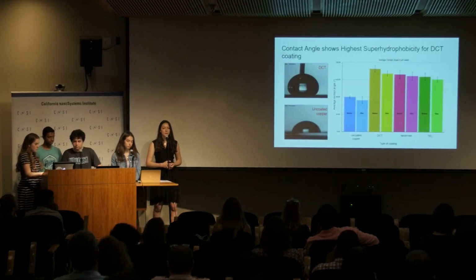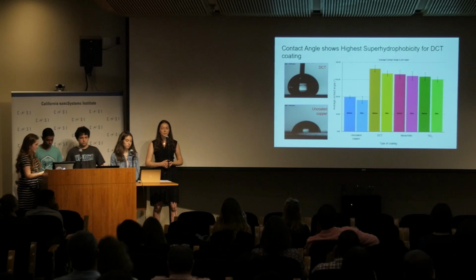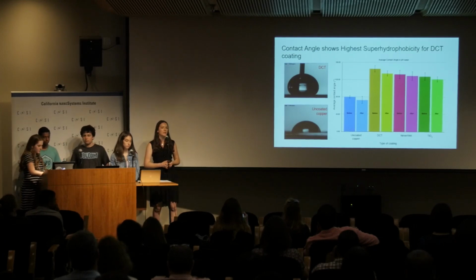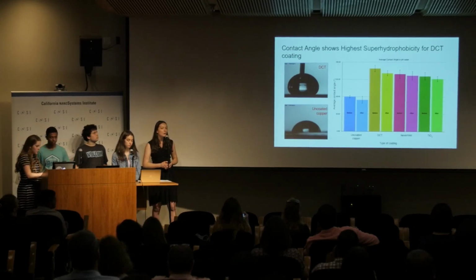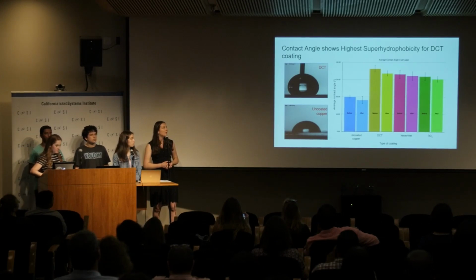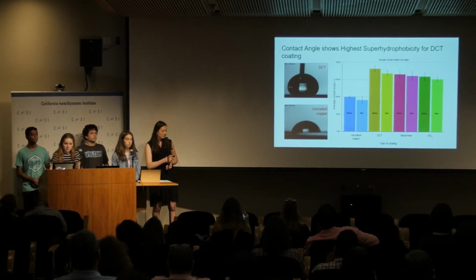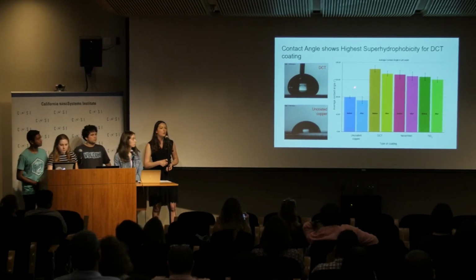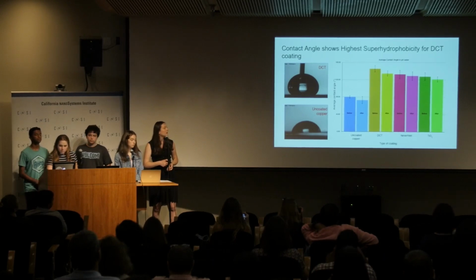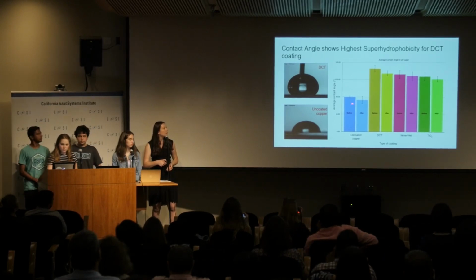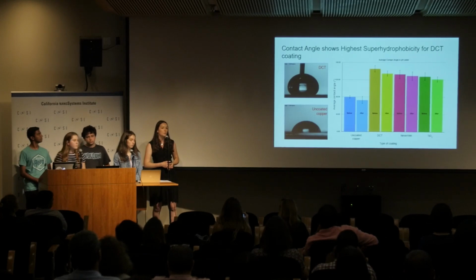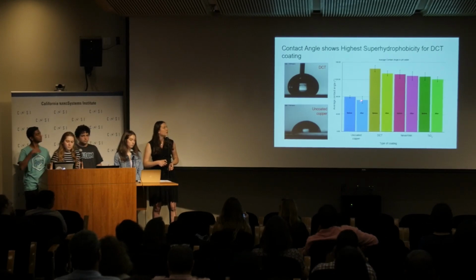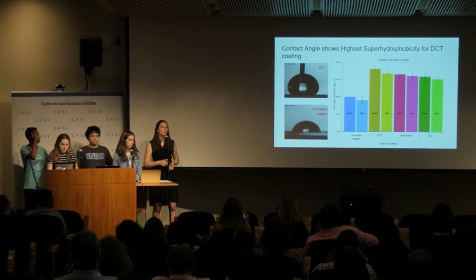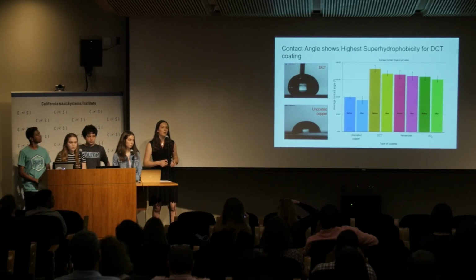And so after leaving the samples in for 18.5 hours, we measured the contact angle again. And what we found is that DCT remains superhydrophobic, as we can see on the graph. So it is the best coating. And the uncoated copper had the lowest hydrophobicity and the highest standard deviation. So some of the samples were really hydrophilic and corroded a lot.